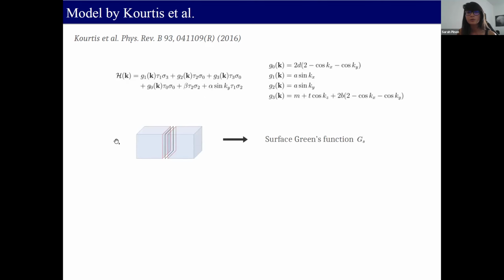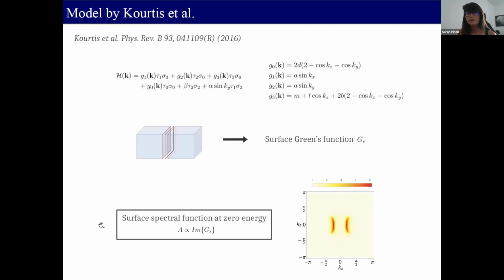The first thing we do is apply our method and compute the surface Green's function for this system. Then we can obtain the surface spectral function at zero energy, which is proportional to the imaginary part of our GS. And we obtain something like this. Here you can see the Fermi arcs appearing. This system has 4 Weyl nodes and 2 Fermi arcs.